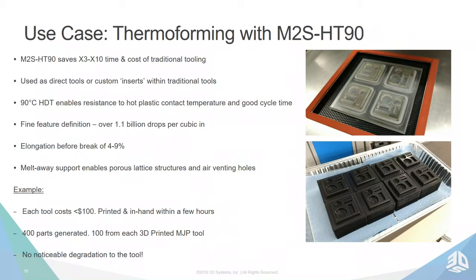So thanks to the fine feature definition of the MJP process, you get over 1.1 billion drops of material per cubic inch of part volume, which means you get really accurate and fine resolution dies or mold surfaces. Another great benefit is that the soluble support material allows you to create porous lattice structures and tiny venting holes for the vacuuming of the final plastic. In the example in the photos here, you see the top photo, we have a mold die printed in the HT90 material. From this part, 400 plastic parts were generated, 100 of them from each of the 4 tools that you see in the top diagram.